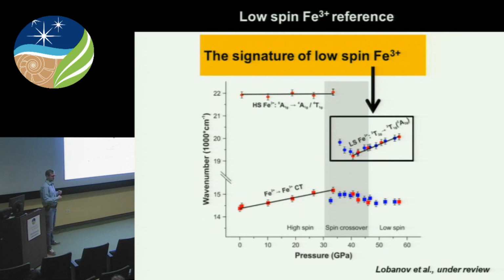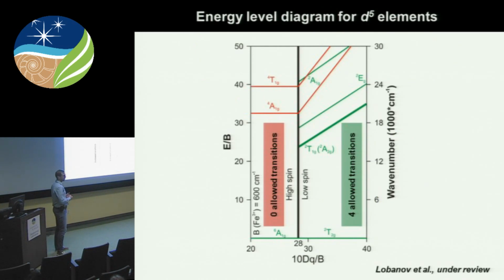You can see that there is indeed a new band that appears at 40 GPa and intensifies up to approximately 50 GPa, and then it remains at a constant intensity, more or less. So we can now plot this absorption band versus pressure, and here the different colored dots just show you compression and decompression data. You can see that the transformations we're looking at are completely reversible, which is in agreement with the spin transition scenario.